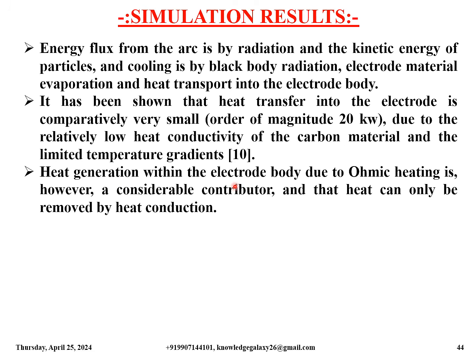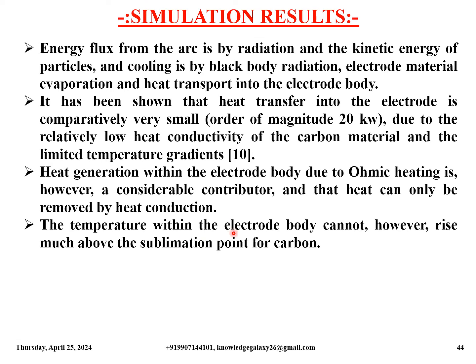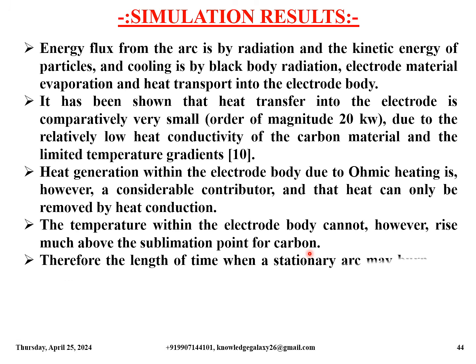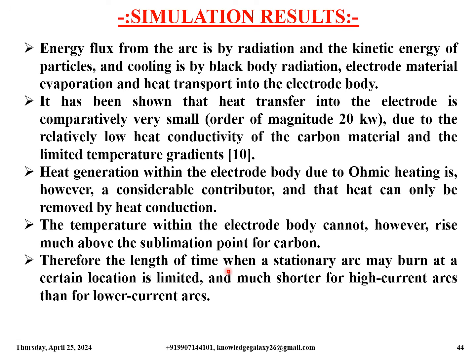Heat generation within the electrode body due to ohmic heating is, however, a considerable contributor, and that heat can only be removed by heat conduction. The temperature within the electrode body cannot, however, rise much above the sublimation point for carbon. Therefore, the length of time when a stationary arc may burn at a certain location is limited, and much shorter for high current arcs than for lower current arcs.